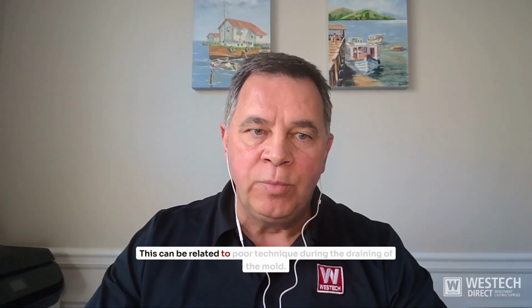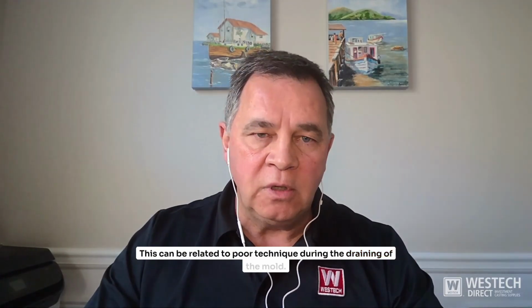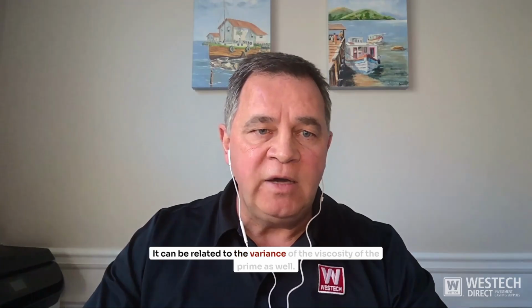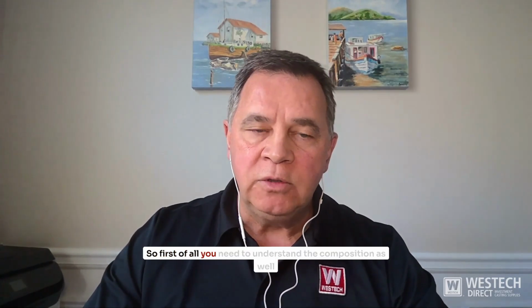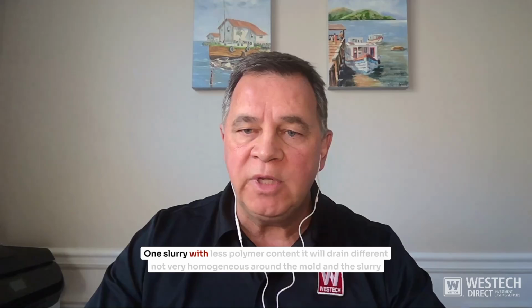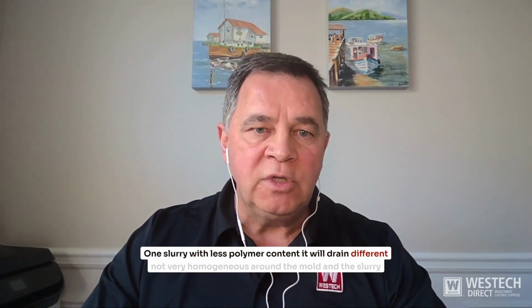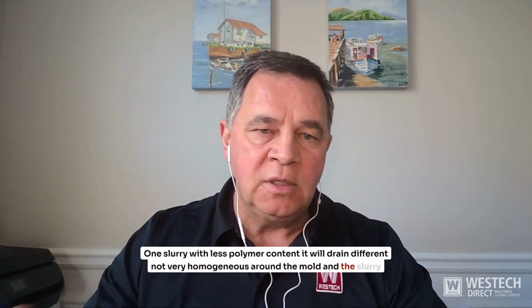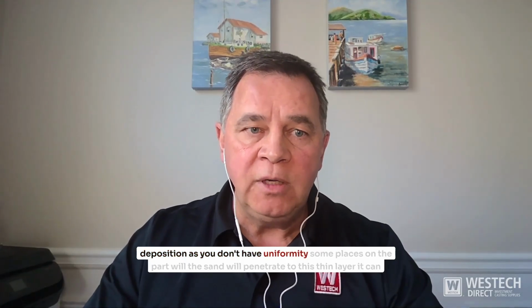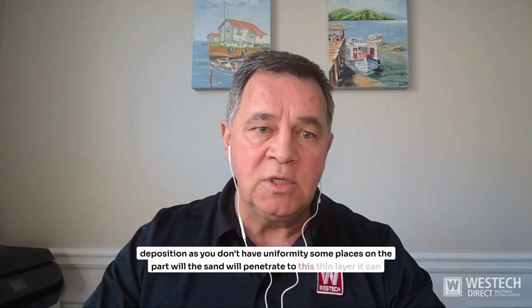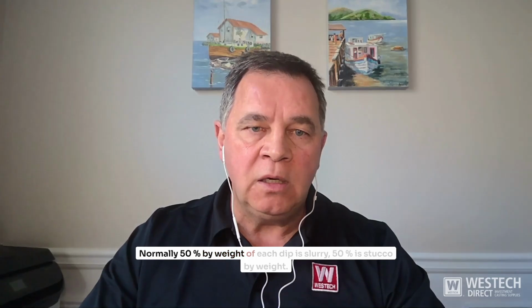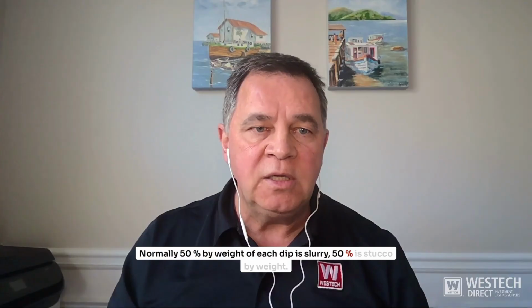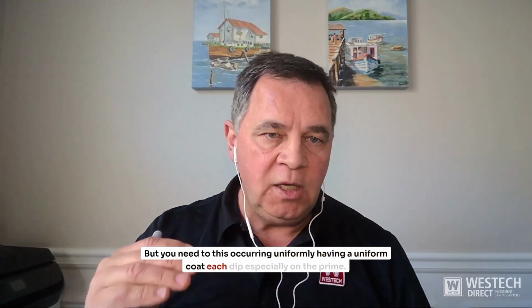This can be related to poor technique during the draining of the mold. It can be related to the variance of the viscosity of the prime as well. So first of all, you need to understand the composition of the slurry. One slurry with less polymer content will drain differently, not very homogeneously around the mold. And with the slurry deposition, as you don't have uniformity, in some places on the part the sand will penetrate this thin layer and can lead to this kind of defect. So our goal is always to look for a homogeneous layer. Normally 50% by weight of each dip is slurry, 50% is stucco by weight. But you need this to occur uniformly, having a uniform coat each dip, especially on the prime.